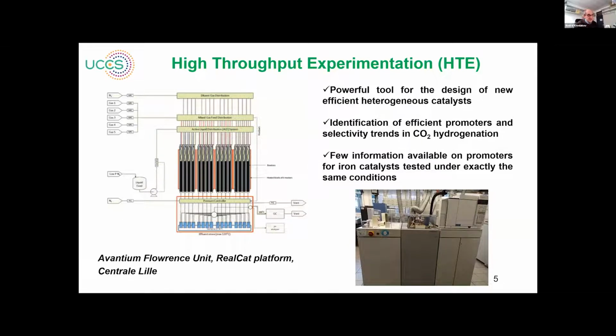It's also very helpful because if we search the literature, we find a large number of papers focusing on CO2 hydrogenation with different promoters. The problem is that sometimes it's difficult to compare, because the promoters were added in different amounts, and also the catalyst synthesis, catalyst test, and catalyst activation, which is very important for the catalyst, have been conducted under different conditions.